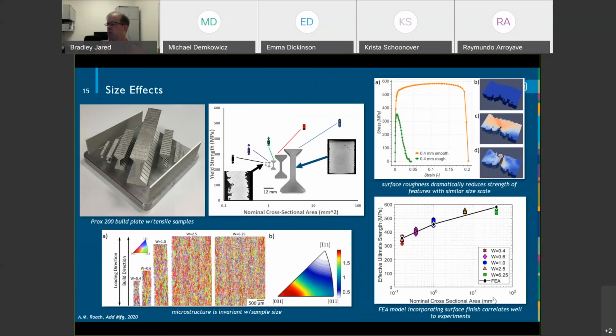And you see a very different response, right? And so we figured this out fairly early on and did some follow-on work, and it showed that essentially what's happening, if you look at the finite element model here, and you can actually characterize the porosity, not on the inside, but the porosity, if you will, on the outside of the surface finish, you actually get a pretty reasonable trend here. So we attribute a lot of this size effect to the surface finish and how you have damage initiation and cracks effectively on the surface, right? And so the problem here is if I have a surface finish, it's fairly constant, right? So my process is going to have, say, a 20 micron surface finish, regardless of the size of this component.